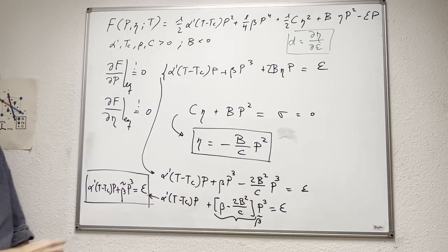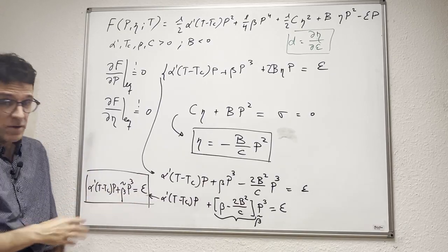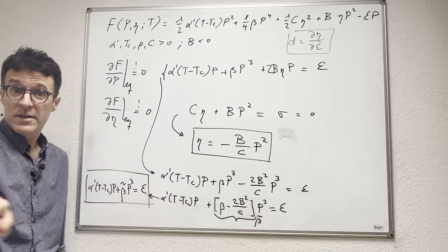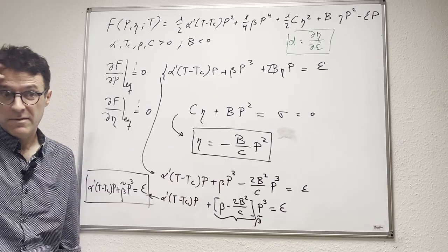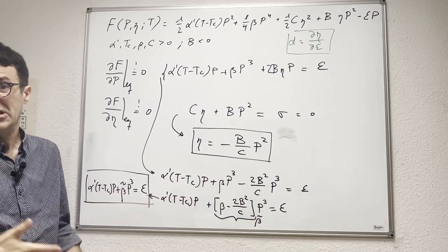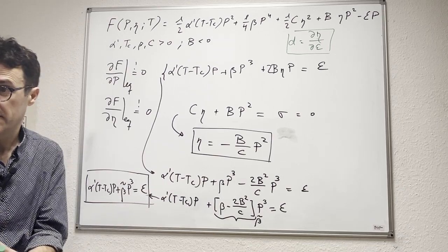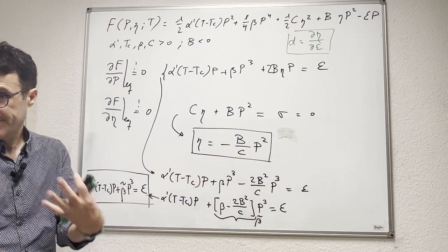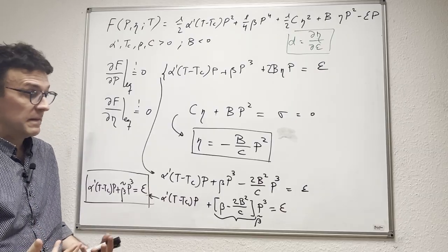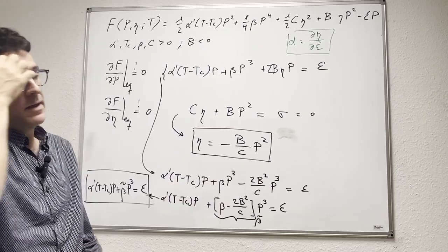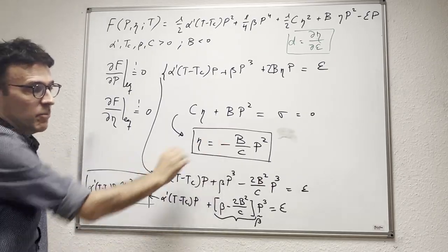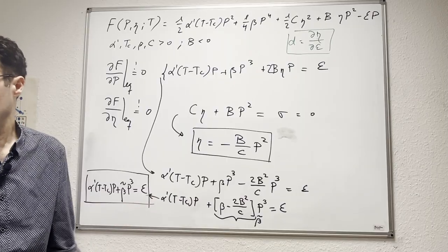When we do that, typically we end up with expressions that, by symmetry, have to look essentially the same as before, but where some parameters have changed. And this new parameter, this beta tilde in this case, is what we call a strain-renormalized parameter. So this beta tilde captures implicitly the effect of having a strain that can relax to further lower the energy when we have a certain polarization and we are at equilibrium.